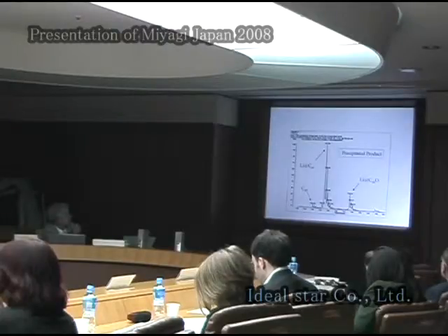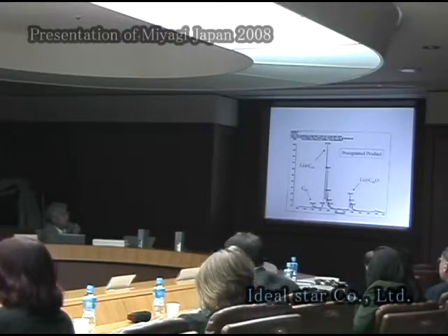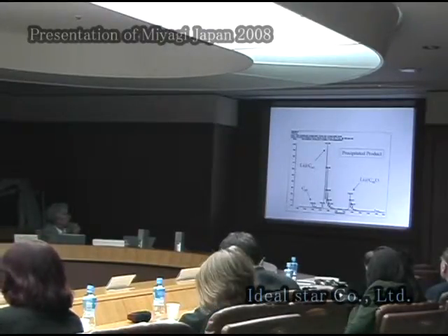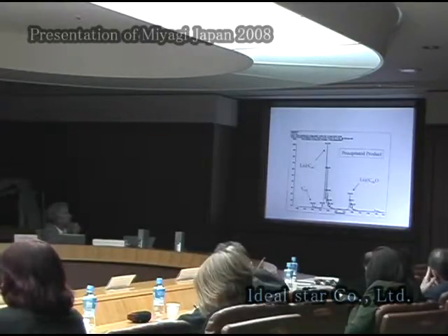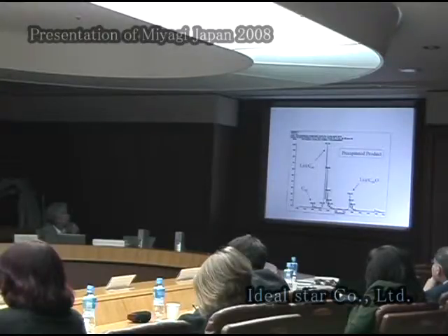The center of the spectrum, that is 727, is lithium fullerene, lithium endohedral fullerene, because the mass number of fullerene, carbon 60, is the mass number of carbon 12 times 60, that is 720, plus the lithium atom of 7, so that is 727, endohedral lithium fullerene.